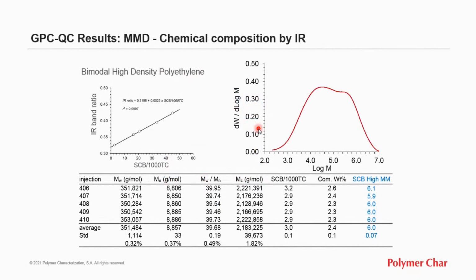As I said before, a very interesting application for that technology is the production of bimodal high-density polyethylene made in a dual reactor process. Lower molar mass high density is typically produced, and a larger molar mass with a small amount of short chain branching is added with some comonomer, and that balance will result in enhanced mechanical properties for pipe applications. From a single GPC analysis, in less than 1 hour, with minimal operator intervention, it is possible to obtain the molar mass distribution, so the relative weight fraction of the 2 reactors, also the polydispersity, the molecular weight of each of the